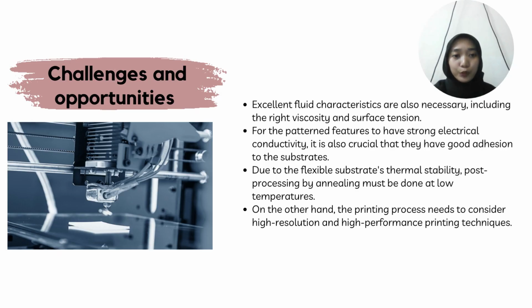For challenges and opportunities, excellent fluid characteristics are also necessary, including the right viscosity and surface tension. For the pattern features to have strong electrical conductivity, it is also crucial that they have good adhesion to the substrates. Due to the flexible substrate's thermal stability, post-processing by annealing must be done at a low temperature. On the other hand, the printing process needs to consider high resolution and high performance printing techniques.